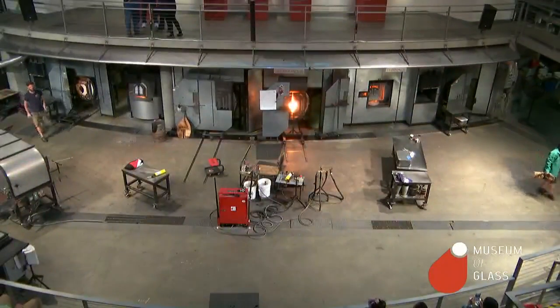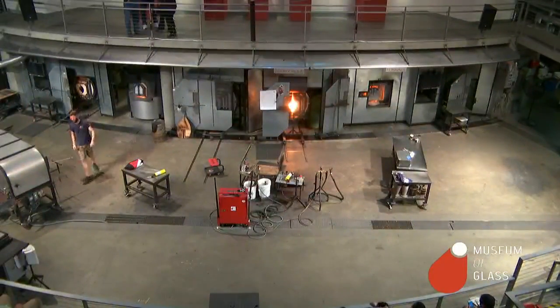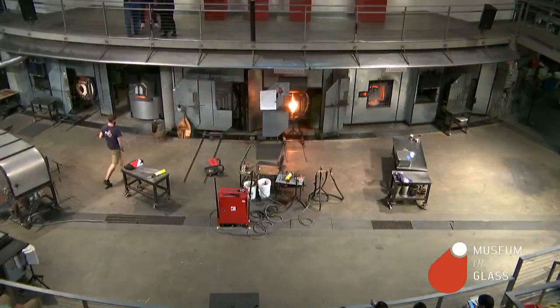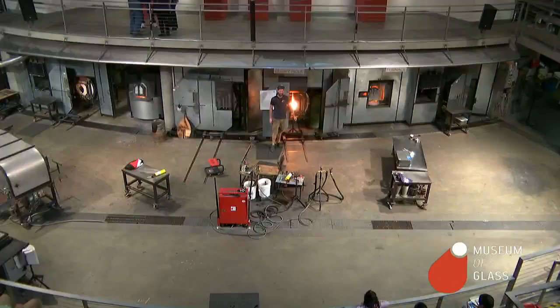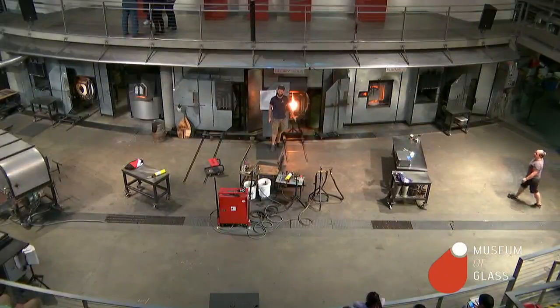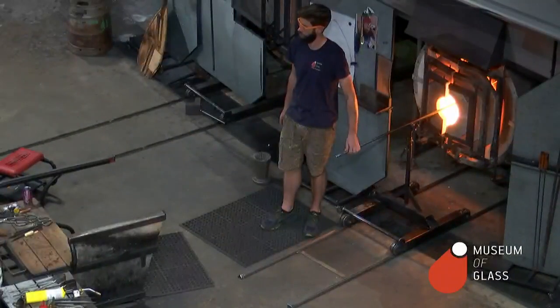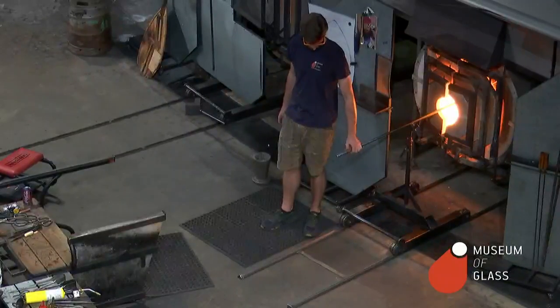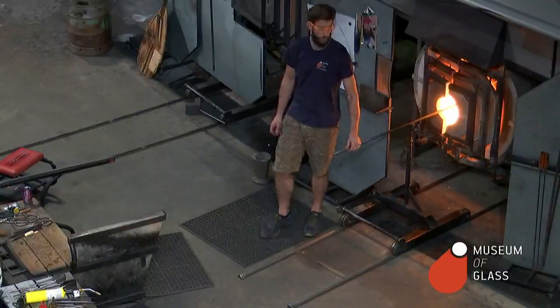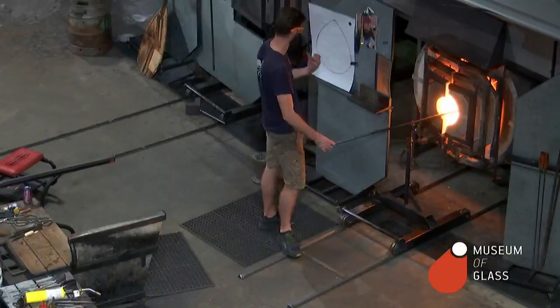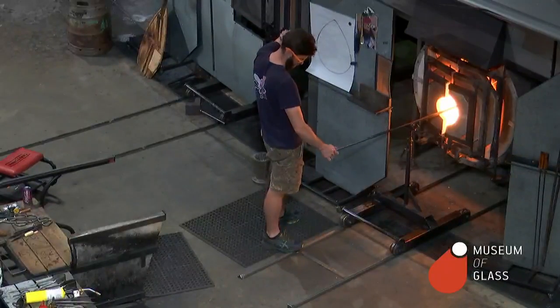So to our audience that is joining us, welcome to the Museum of Glass. Everything that we make here will always go through an annealing cycle. We will place it in the annealer on your left-hand side, sitting at 920 degrees. It will cool back to room temperature over the period of 10.5 hours. This will eliminate any stress that may be built up in the glass, preventing it from breaking or cracking.